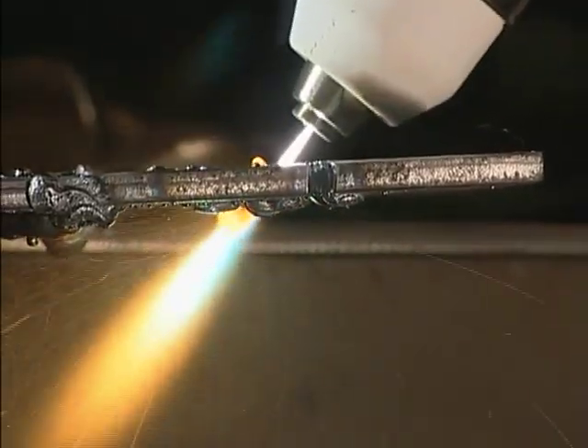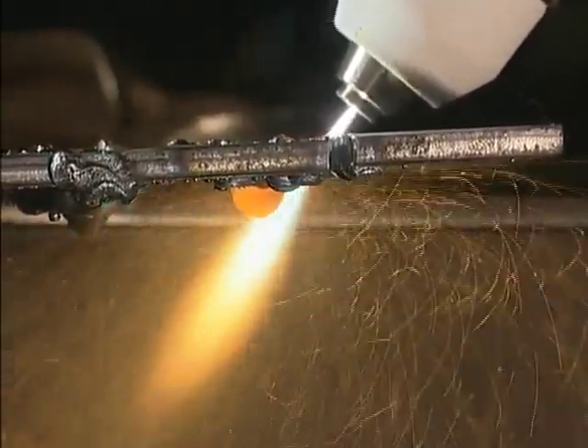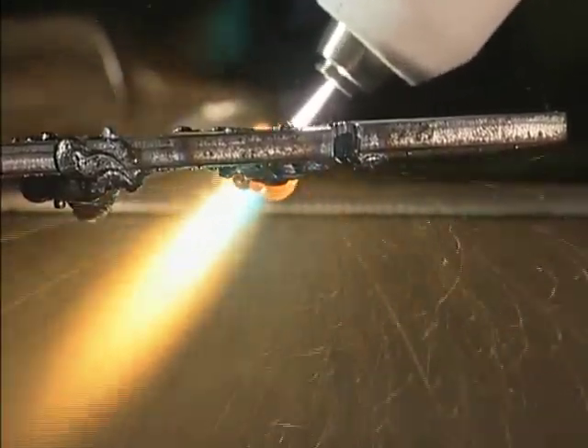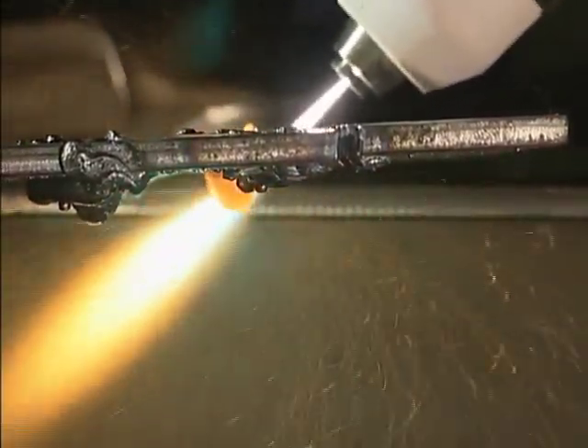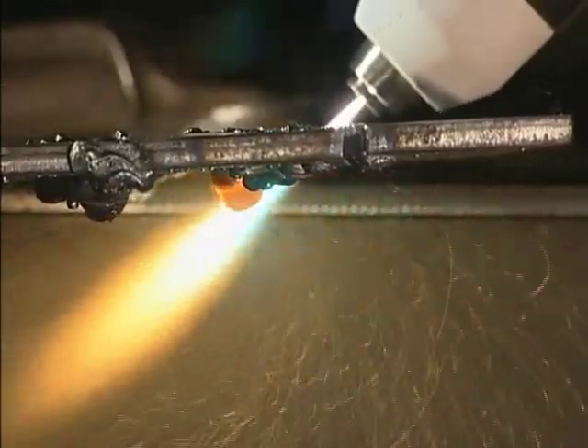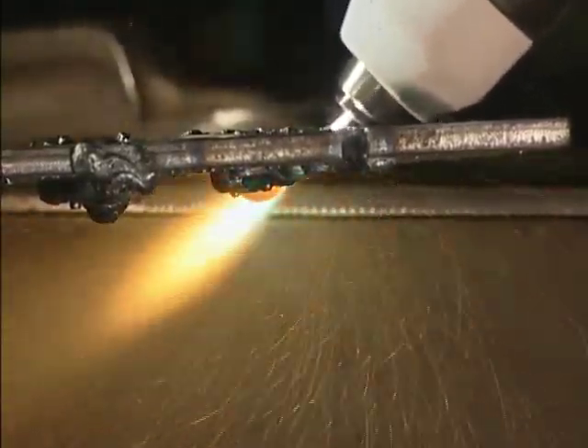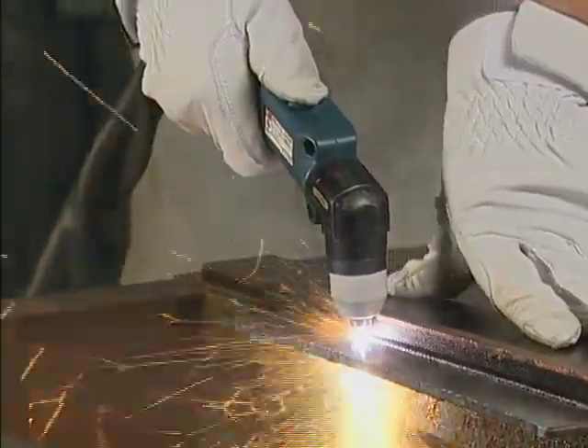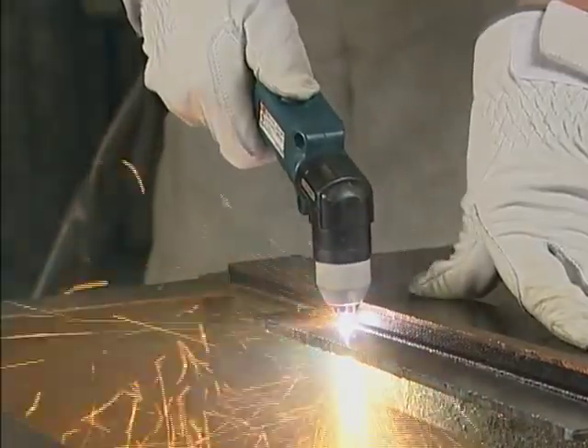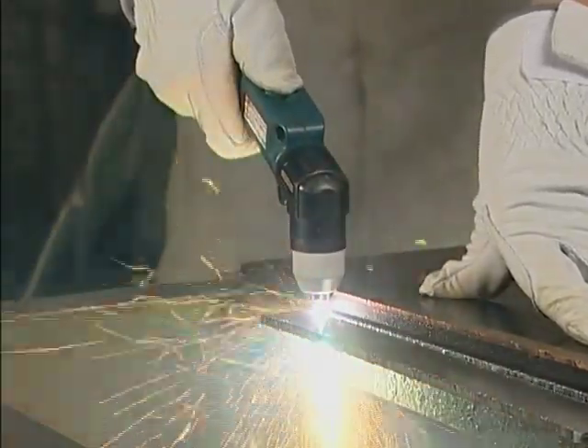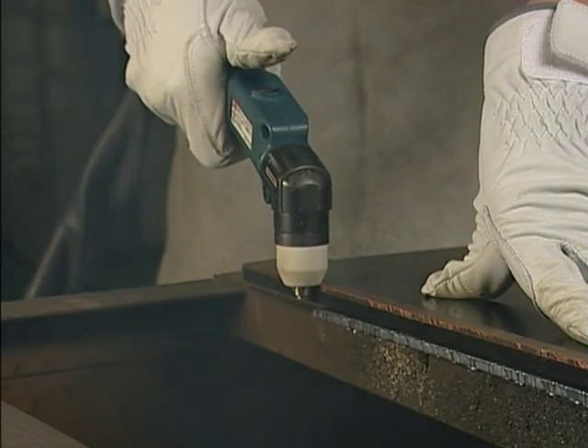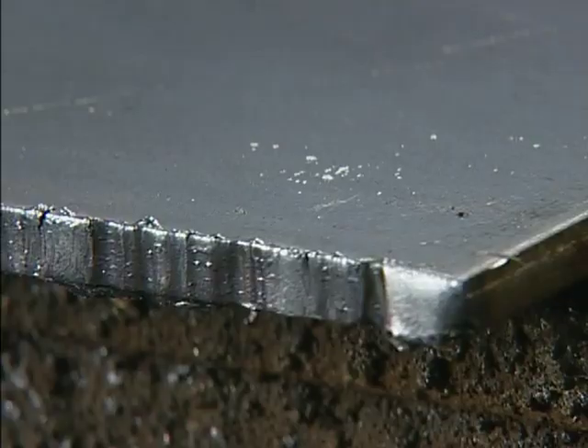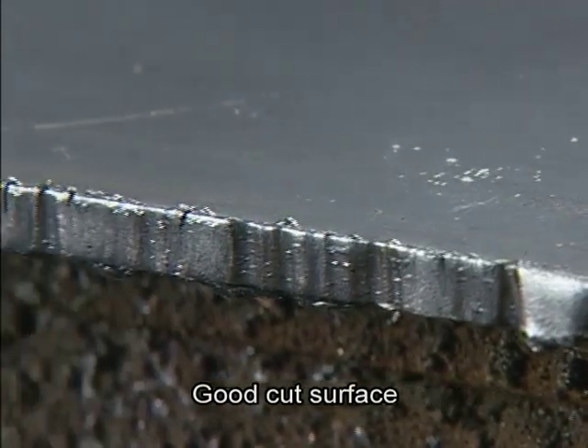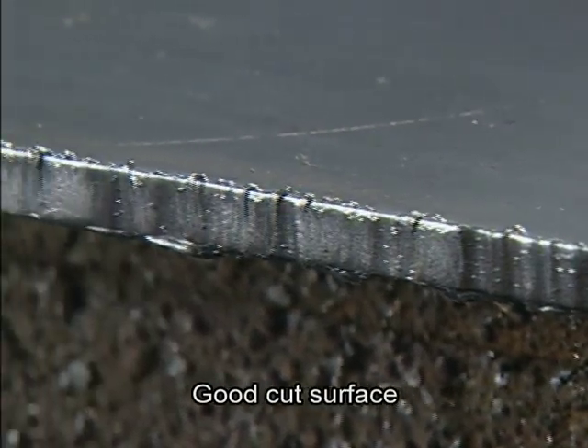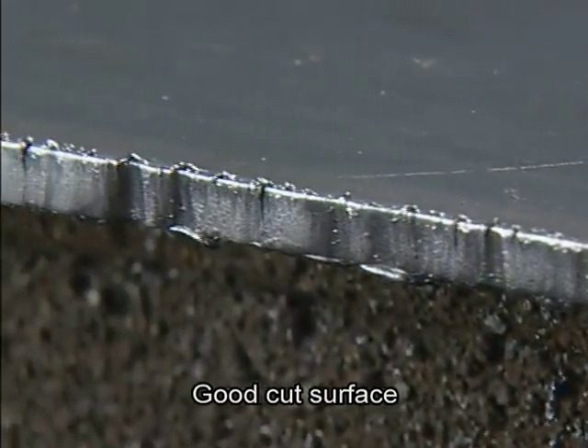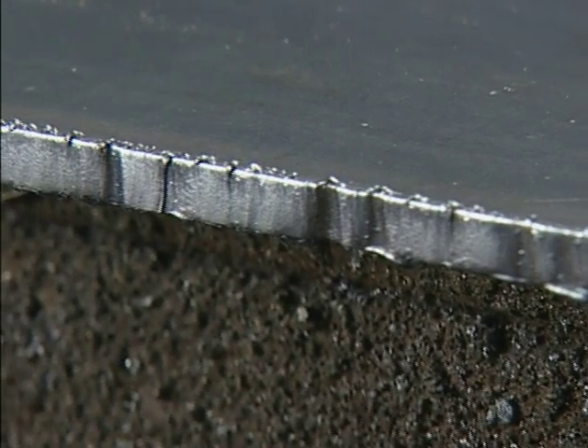If the torch inclines to one side of the cutting line, spatters will fly to the other side. Use this clue as a yardstick to determine if the torch is upright. At the cutting end point, turn off the torch switch to complete the cut and keep the torch immobile for the duration of afterflow. Inspect the cut surface. If it's markedly deformed, check the electrode and the tip for abnormalities.